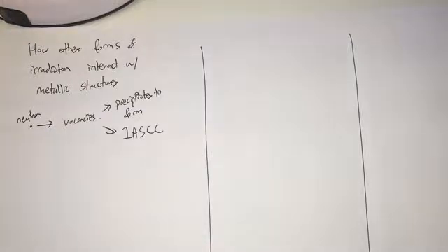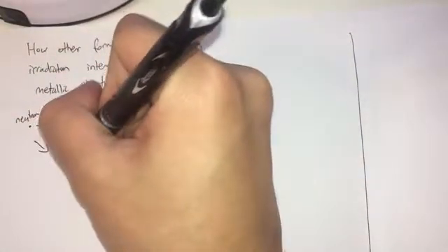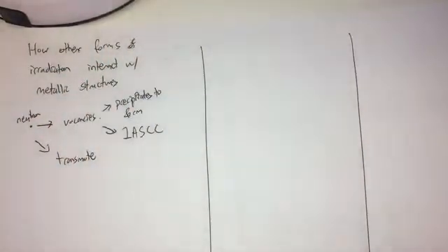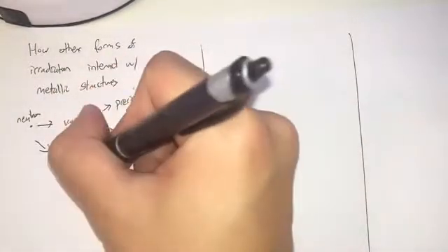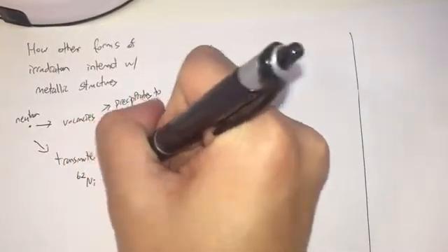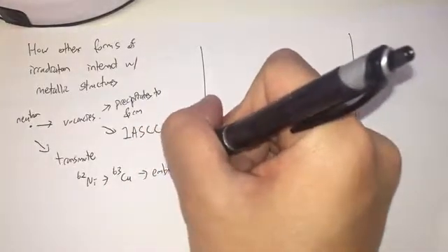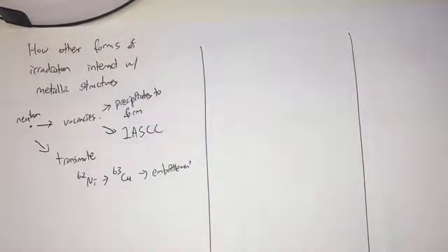So these can actually cause some corrosion to occur, and this will eat into the steel. And we've also discussed how a neutron can transmute, for example, nickel into copper, nickel 62 into copper 63, and how that can cause embrittlement because of the formation of copper precipitates. So that's already discussing neutron irradiation in general.